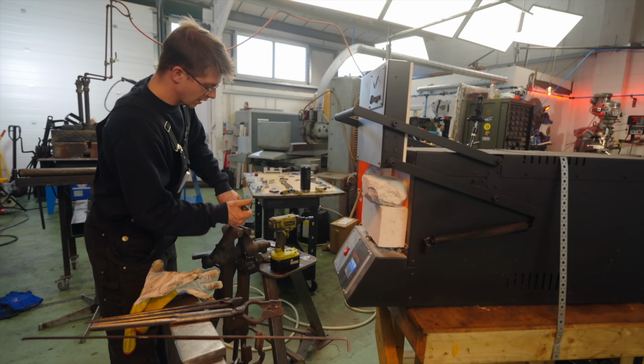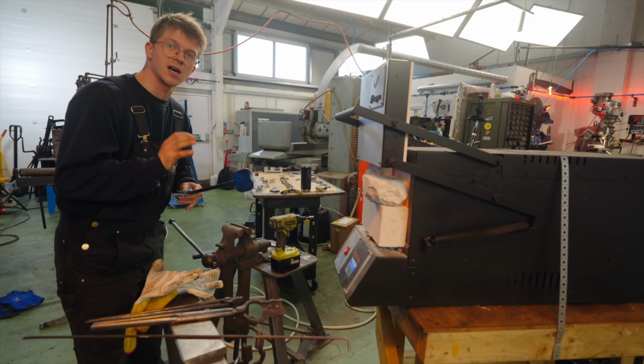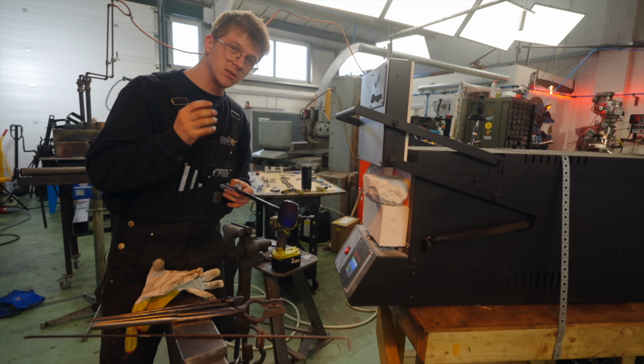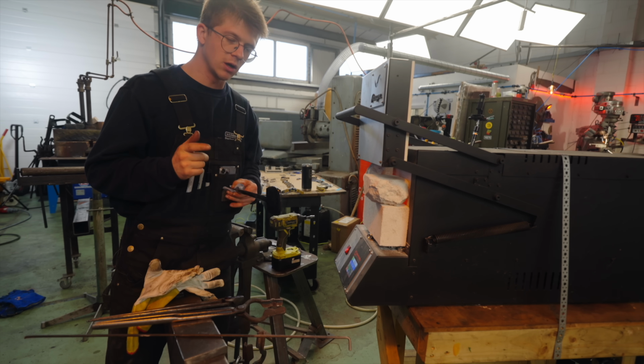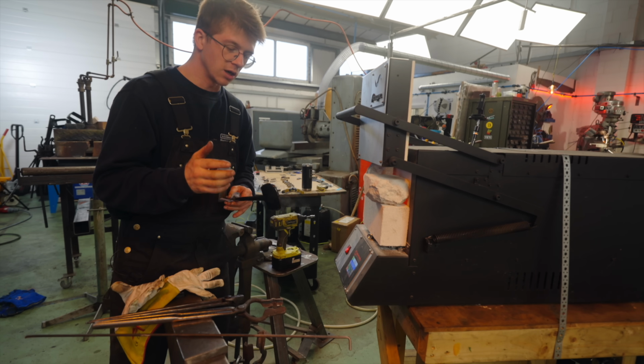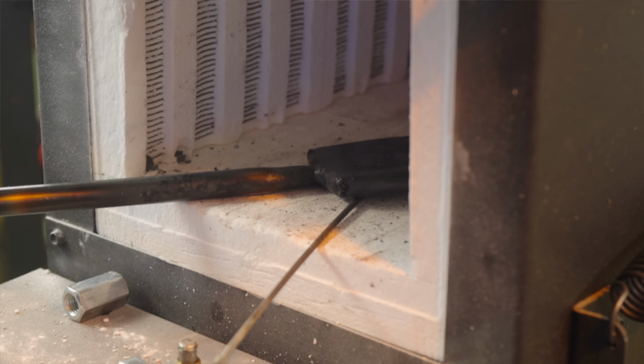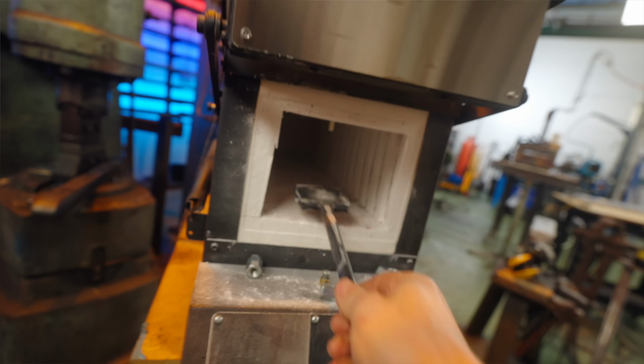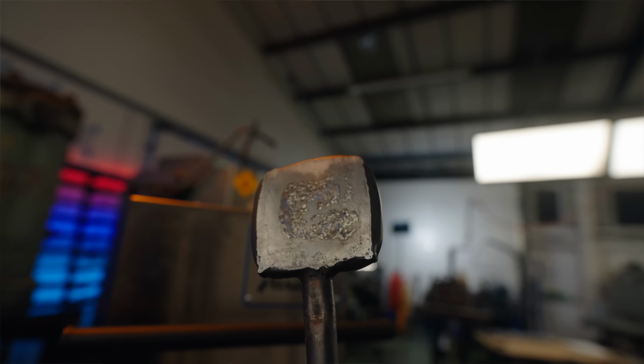All right, we're going to need to run a slightly different order of operations because obviously I'm not going to be able to cut the hardened steel and process it to size. And also, if you leave steel hardened but not tempered for too long, the steel itself can break. So we're going to dump the heat out of the kiln, temper it as soon as possible, and this is then going to be the perfect time to use the water jet again, because it will be impossible to bandsaw the hardened steel.